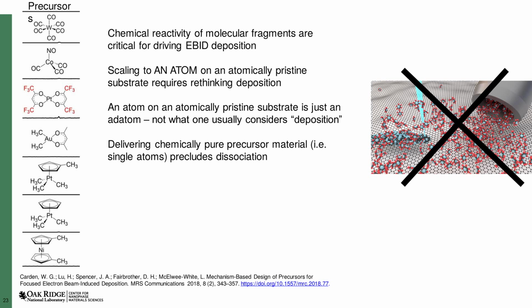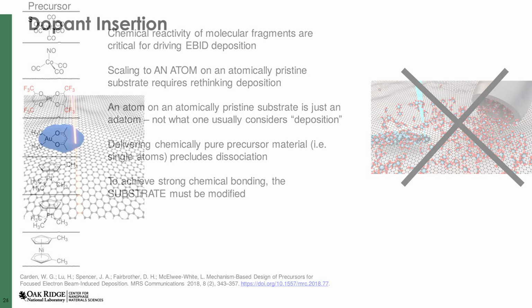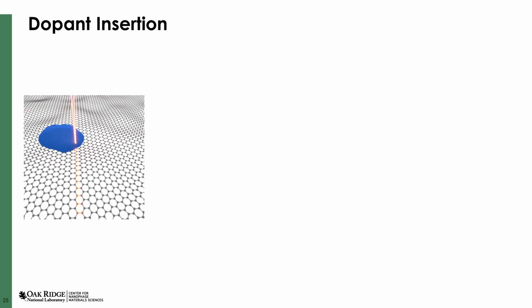Nevertheless, there is a way forward, and the solution offers itself by grappling with the problem of exactly what it is that we want to have happen. We cannot ignore the fact that we do not have a clear picture of deposition on the single atom scale. Once we realize that we need strong chemical bonding between the substrate and the atom, and that we cannot modify an atom, we come to the inevitable conclusion that we must modify the substrate. What will this look like? Here's a conceptual model. We start with the graphene substrate, and on top of the graphene, we have our source material. We would like to get an atom from the source material into the graphene lattice.